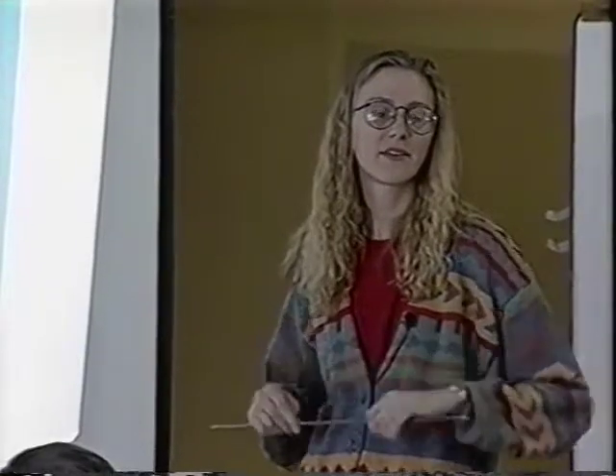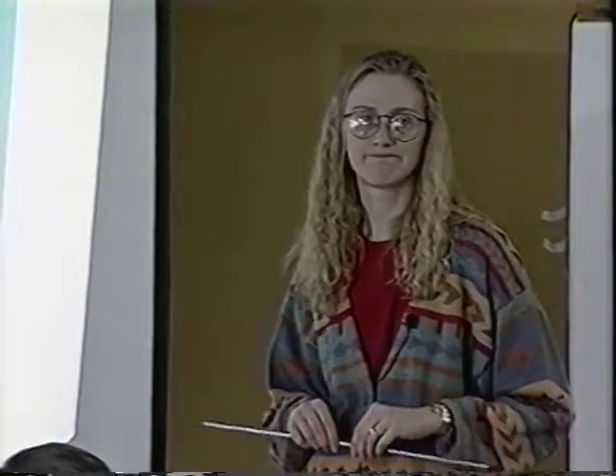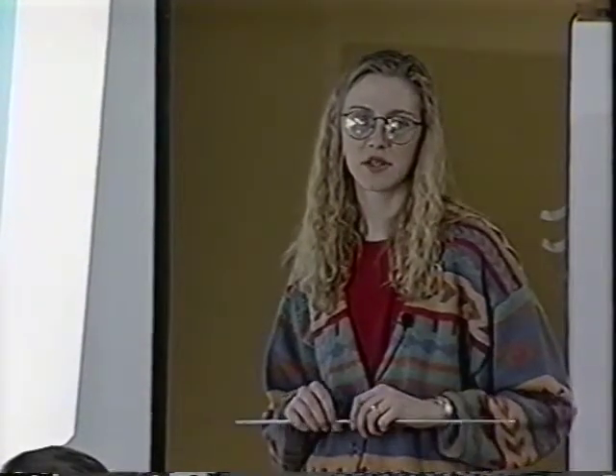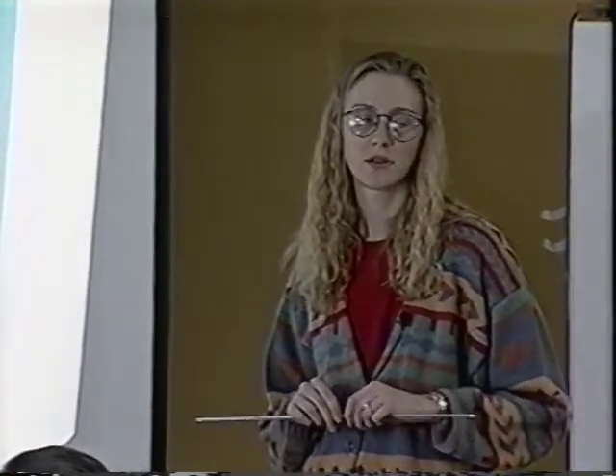Yeah? Are your coils stored on the edge or on the flat surface? Both. At 1,000 to 1,400 degrees, will that create a flatness in the steel, storing it on the flat? If it's belly down, it can. Some chemistries are more prone to that than others. I work with one chemistry that, when you get even near 1,200 degrees, just sags right down. I'm trying to think of a way I could put something in the eye to hold it up. I'm still working on that. And I think about it at night. How could I get those to stop from collapsing? Yeah, and others are just happy as punch sitting belly down. If we're going to be processing it inside somewhere, we leave them eye up. But if it's going to be sold as a black band, they're put belly down within a day or so.